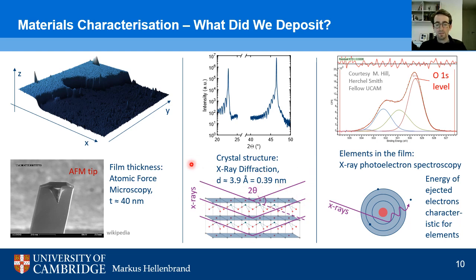So in the first case, we measure the diffraction angle. If we have a nice atomic structure which is very regular, again, remember one of the slides before, and incoming X-rays encounter this crystalline structure, they will be diffracted at a certain angle which depends on the distance between the atoms. So by measuring the diffraction angle, which is called 2 theta here, we can measure the distance between atomic layers. This is illustrated in the figure down here.